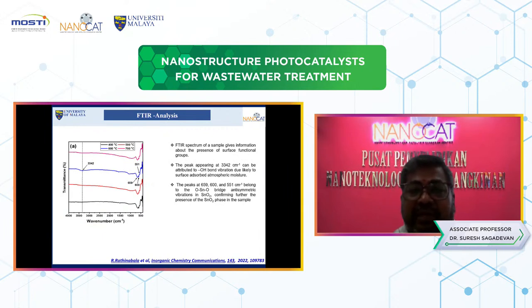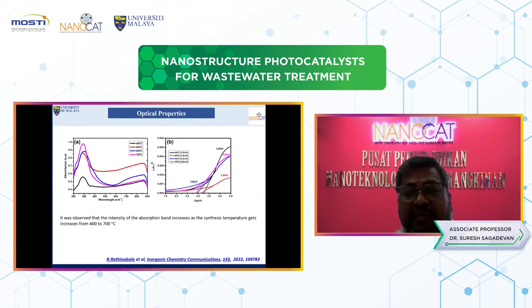Look at here, the peak values at 659 and 600 and 500 confirm the O-Sn-O anti-symmetric vibrations and stretching vibrations, which confirms the presence of the tin oxide particle. And as well as we performed the optical properties by using UV absorption spectra. From the UV absorption spectra, the intensity of the absorption band increases as the synthesis temperature increases from 400 to 700 degrees Celsius. And the bandgap value was calculated by using the Tauc plot.